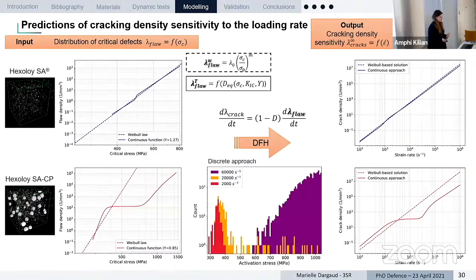In order to understand better this phenomenon, we've developed another approach based on X-ray tomography, but which is a discrete approach in which we capture the defects during the tomography scan at the exact same position and with their size. And from this, we create a numerical volume on which we are going to do tensile loading at a given strain rate. And at a given strain rate, we can actually identify which were the pores which were triggered in the configuration. So here you have a histogram where for a given strain rate, you have the population of defects that was triggered. So at low strain rate, what happens is that we only trigger the largest pores.